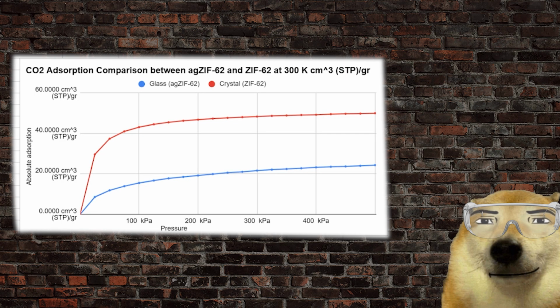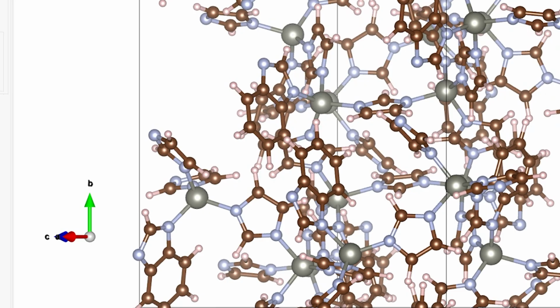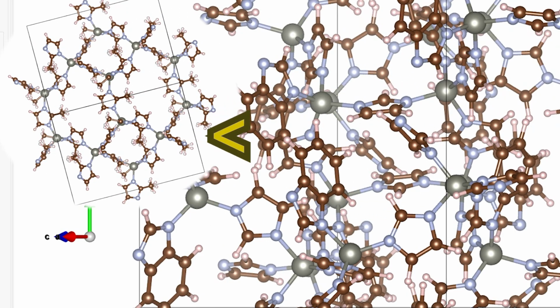What's more interesting is the shape of the adsorption curve. For ZIF-62, the uptake increases rapidly at low pressures and then gradually levels off towards saturation. This is not a simple linear behavior, and it highlights something important. ZIF-62 performs particularly well at low pressures. This makes it especially relevant for applications like passive carbon capture, where CO2 concentrations are relatively low.